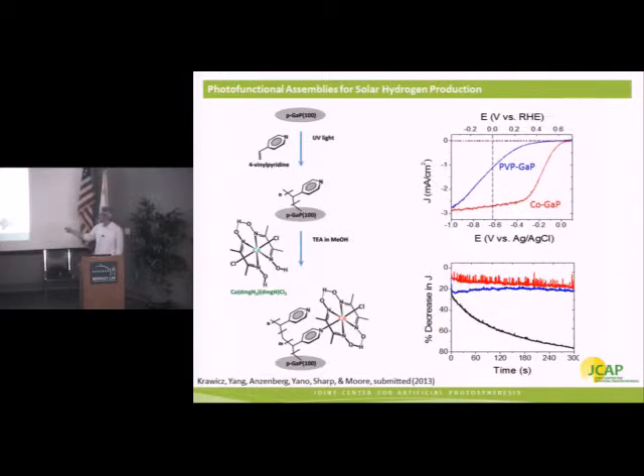In contrast, as soon as we have the polyvinyl pyridine layer on the surface, it's not a very good photoelectrode, but it's a stable photoelectrode. That's shown by blue here. In red, we have good photoelectrochemical performance, as shown by the curve on the top, and also stable performance. So this is an example of a catalyst derived from a molecular system attached to a photocathode that is functional and stable in aqueous environments. This is exactly what we're looking for.